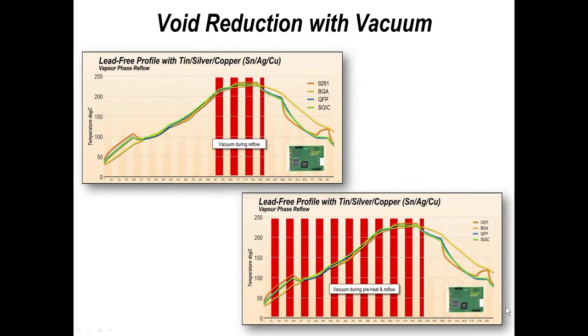Now, another conversation, and whether this is important or not, there's still lots of discussion on this, is the use of vacuum. But vacuum does work. There's no question that if it's a critical application, you have to remove voids from solder joints, then vacuum is something you can do, and not change other process parameters like materials, etc. But normally speaking, by enhancing the process that you're running, you can reduce void formation.